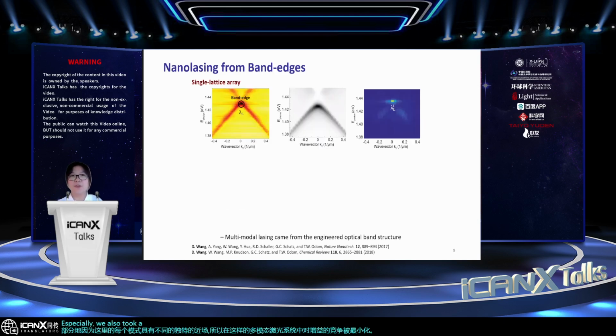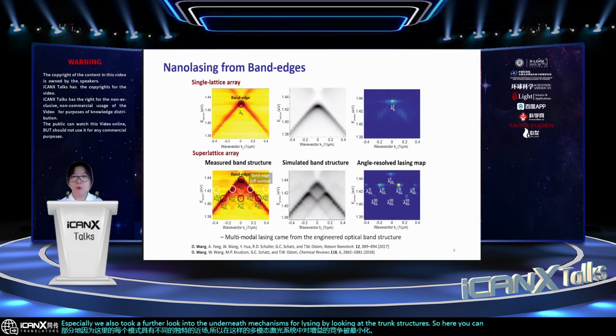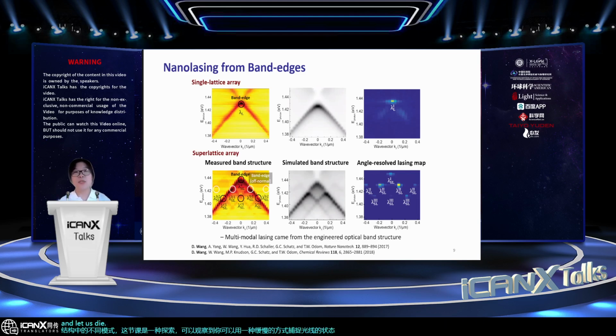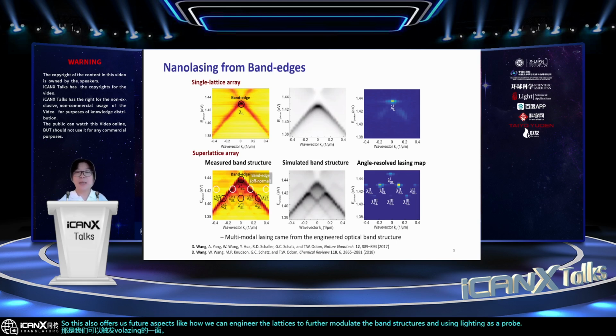Especially, we also took a further look into the underlying mechanisms of lasing by looking at the band structures. Here you can see both the modeled and the measured optical band structures from such a superlattice, where you see multiple band edge states. We found a pretty good correlation between the lasing emission position and the band edge position, which means that, based on the superlattice, we're engineering the dispersion of the different modes in the band structure, and the lasing is serving as a probe to look at the band edge state, where you can trap the light in a slow-wave fashion with nearly zero group velocity, and that's a site where we can trigger lasing. So this also offers us future aspects, like how we can engineer the lattices to further modulate the band structures and use lasing as a probe to look at what is happening inside.